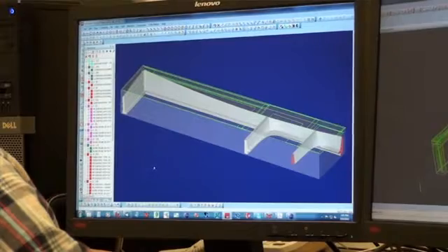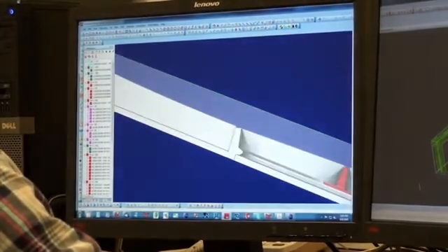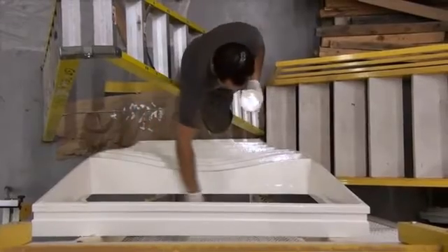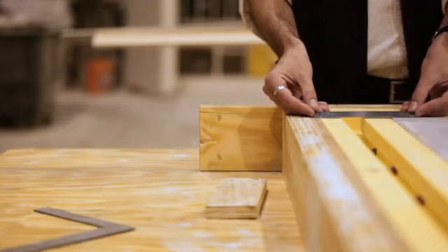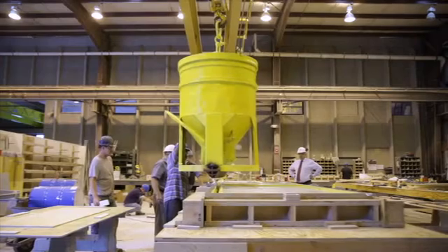The first step in the process is done by the architects and engineers — we've designed a digital model of the liquid wall panel. That model is then used for a CNC milling process where a machine reading the digital model cuts the positive form out of expanded polystyrene, creating a positive from which the negative rubber molds are built, and those rubber molds are used for the concrete casting process.